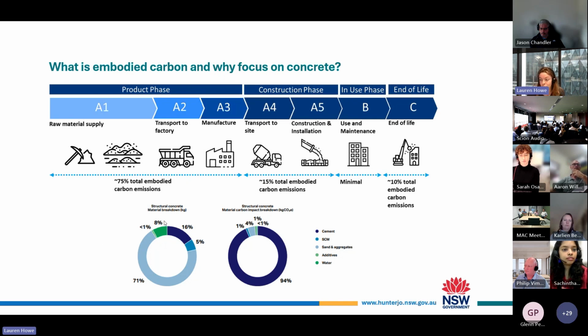This graph at the bottom, or pie chart, just shows the breakdown of concrete by mass. Around 16% of a typical mix is your cement. But when we look at it from an embodied carbon footprint perspective, over 90% of the carbon of that concrete is from the cement. And the good thing here is we have a big opportunity to start to reduce the amount of cement that we use in our mixes.